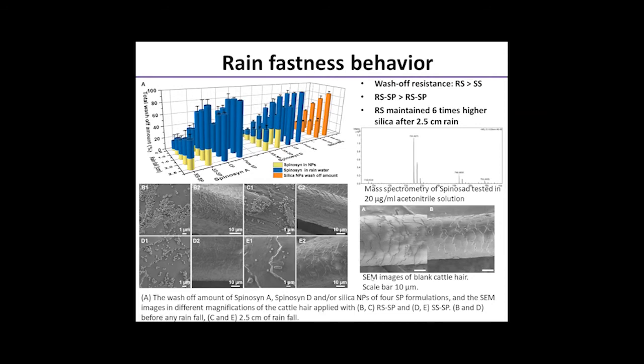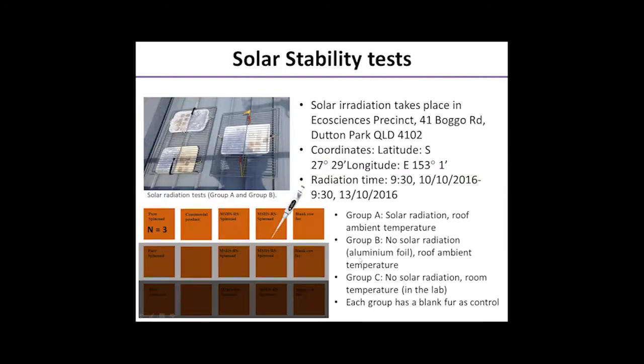resistance towards rainfall. The solar stability test of nanospinosad was conducted in natural solar radiation to simulate the field condition. Cattle hide pieces with 4 spinosad formulations were divided into 3 test groups. Group A was placed on this rooftop and exposed to both solar radiation and ambient roof temperature. Group B was placed on the rooftop with ambient temperature, but covered with aluminum foil to avoid the direct solar radiation. Group C was placed in the lab with a constant room temperature of 21 degrees C and protected with aluminum foil from the UV radiation.